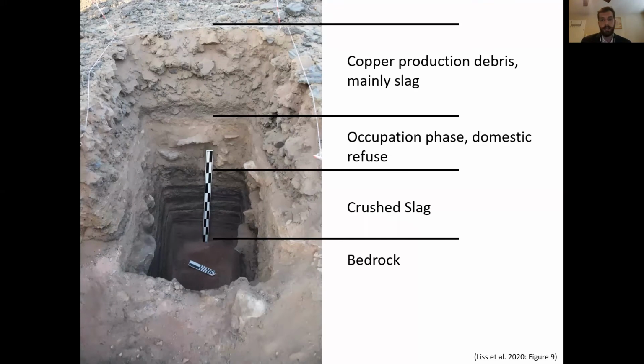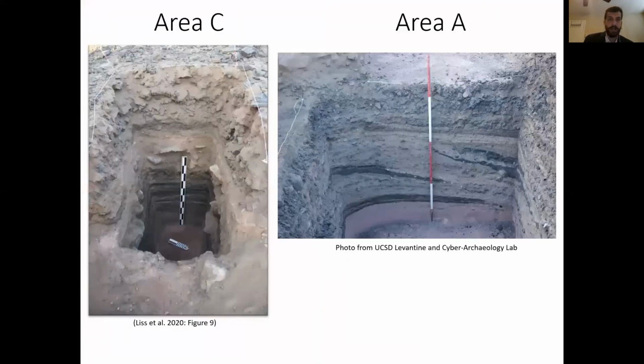Just to summarize the excavation results, we identified 3 main layers above bedrock. Immediately above the bedrock was a pretty thick accumulation of crushed slag, almost 80 centimeters thick. This transitioned into a more domestic or habitation phase, which lacked slag altogether, but had more domestic refuse. And then on top of this was another thick accumulation of slag, which had not been crushed and included some larger slag cakes.